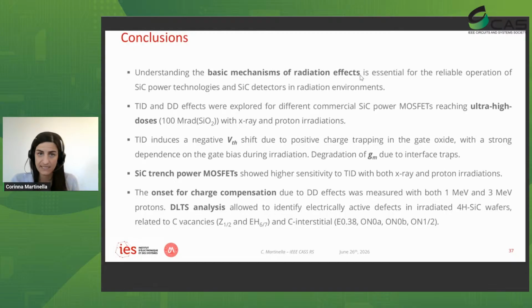We can say that in all these cases, we observe a negative shift of the threshold voltage due to positive trapping of charges in the gate oxide. There is a strong dependence on the gate bias during the irradiation. And also we studied the degradation of the transconductance in order to understand the quality of the interface. We observe a higher sensitivity with the trench power devices with respect to the planar ones. And also we were able to identify the onset for the charge compensation that is induced by displacement damage with different energies, and also to use DLTS and other spectroscopy techniques to analyze the presence of defects and also of strain within the silicon carbide crystal.